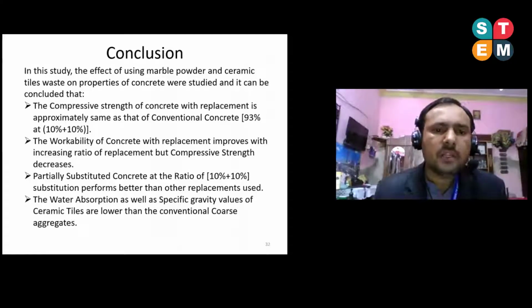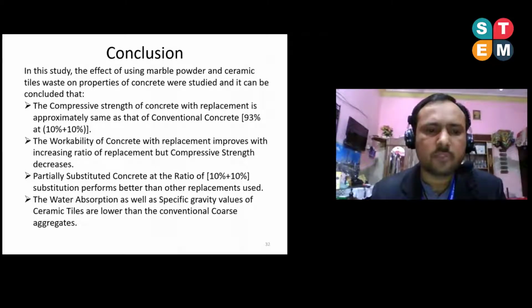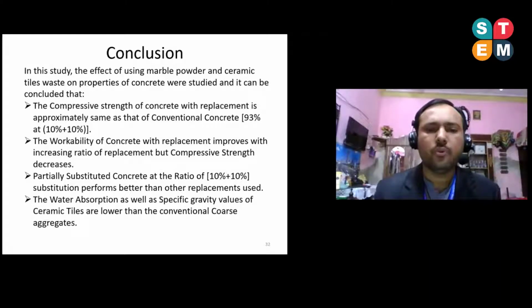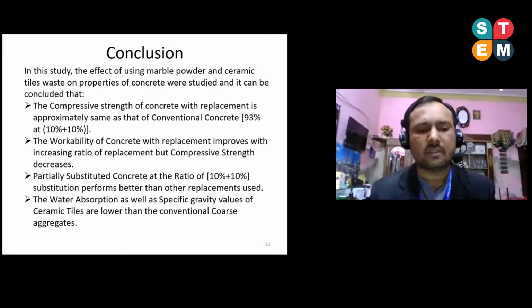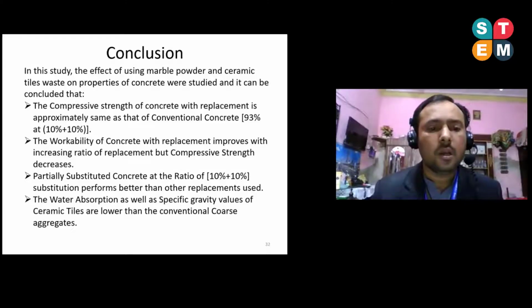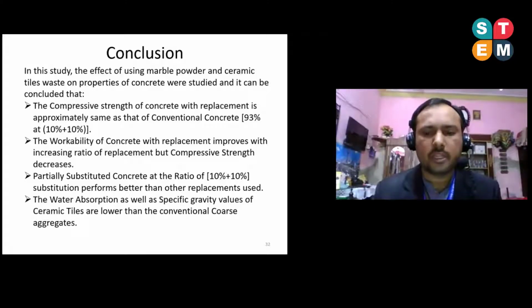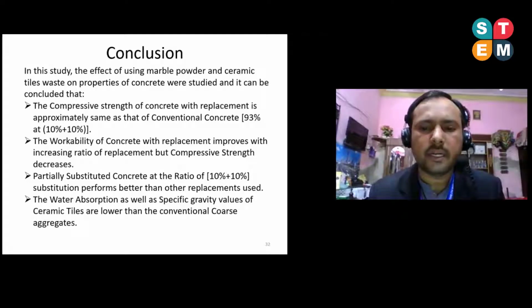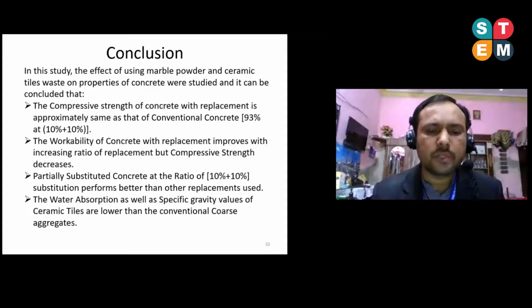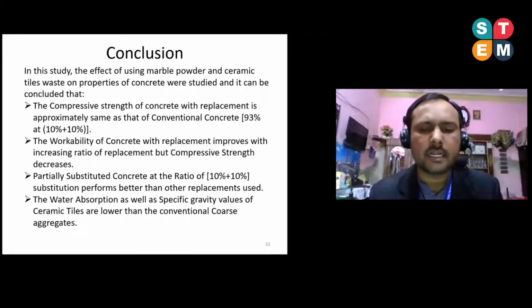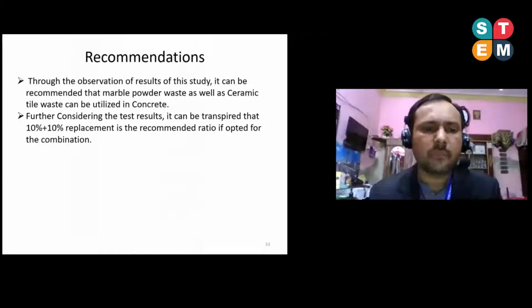In this study, the effect of using marble powder and ceramic tile waste on properties of concrete were studied, and it can be concluded that the compressive strength of concrete with replacement is approximately same as to the conventional concrete. So the workability of concrete with replacement improves its increasing ratio of the replacement, but compressive strength going to be decreased, but not at a huge amount. Partially substituted concrete at the ratio of 10 plus 10 substitution performance better than other replacement usage. So this study also recommended that 10% marble powder and 10% ceramic tile as an optimum. So the water absorption as well as the specific gravity values of ceramic tile are lower than the conventional coarse aggregate. So these are some recommendations.